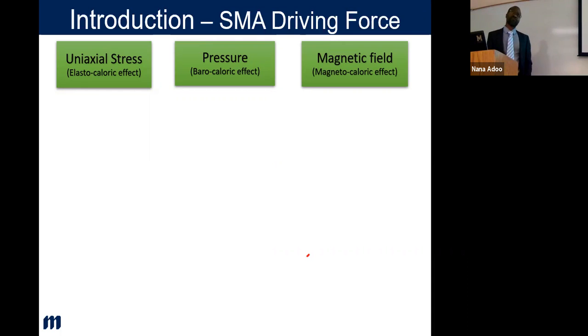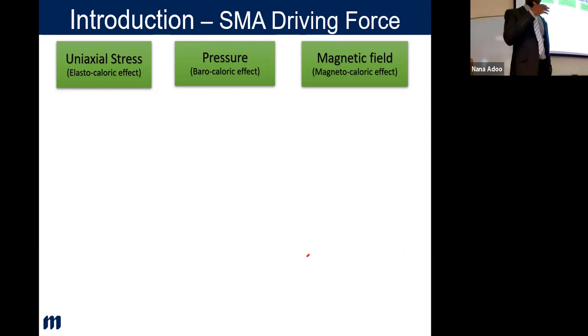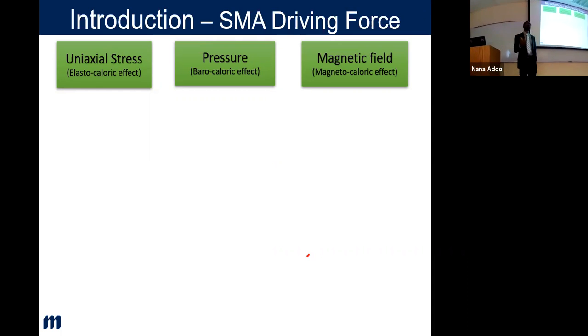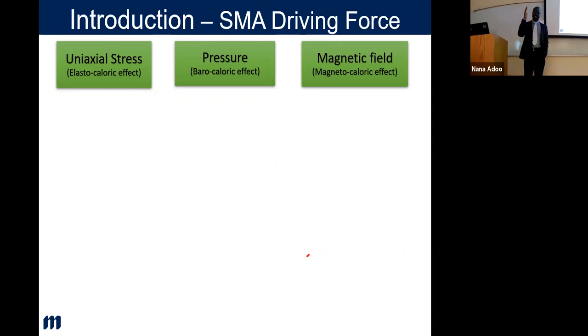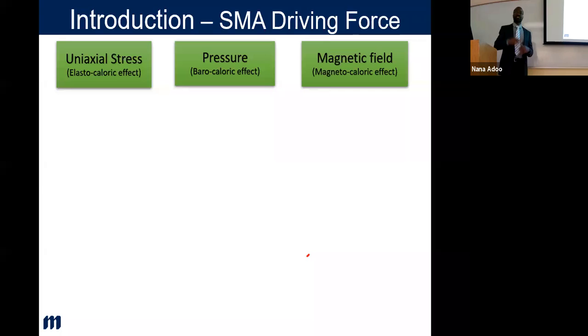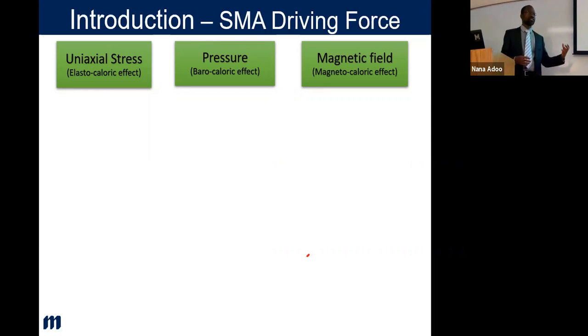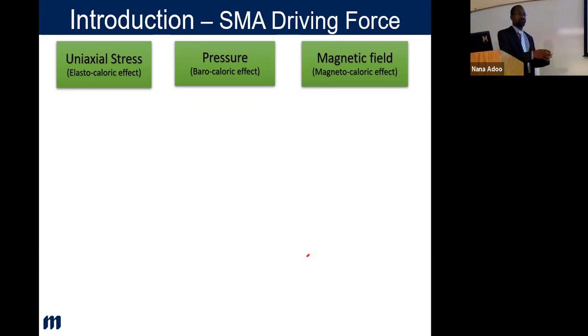Now, nickel manganese gallium is a ferromagnetic material, in the sense that when you subject it to a magnetic field, it aligns all its magnetic axes to it, and that ramps up the energy. It increases the magnetism of the material, and induces a magnetic field induced strain, which is large, and gives off a large heat because of that. So it's coupled to the heating, giving it more energy to get out. And so we have a large MCE, which is the magnetocaloric effect, as well as the field-induced strain.